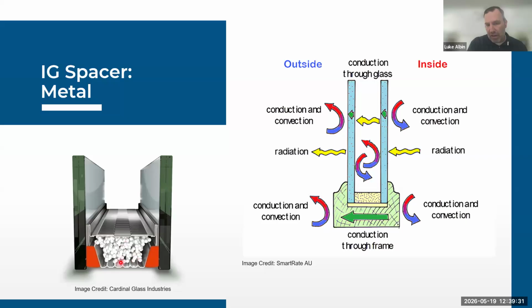And this white area here is desiccant. There is a little bit of a weep system, so any incidental moisture that is in between the panes of glass in manufacturing can be pulled down and put into this desiccant area. However, as you can guess, metal is very conductive from a heat transfer standpoint, and that's what we're trying to get away from.